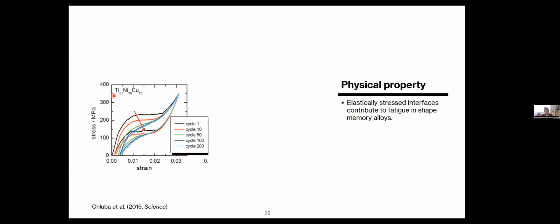researchers have done, if you take an example of a shape memory alloy made of titanium, nickel, and copper, and you cycle this material over 200 times. Here is an example where the phase transformation was induced by mechanical loads. And so this is your cycle 1, that's in black, and you cycle it repeatedly for 200 times. Your 200th stress-strain cycle looks quite different from your first one, or in other words, the material develops fatigue.